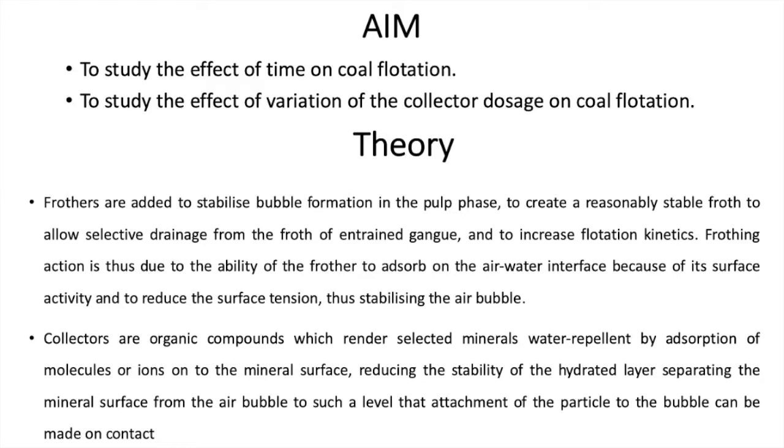Collectors are organic compounds which render selected minerals water repellent by adsorption of molecules or ions on the mineral surface, reducing the stability of the hydrated layer separating the mineral surface from the air bubble to such a level that the attachment of the particle to the bubble can be made on contact.